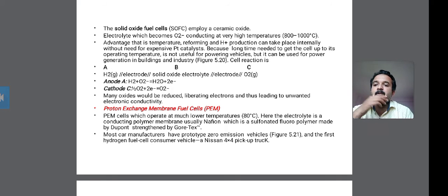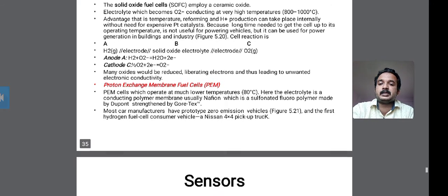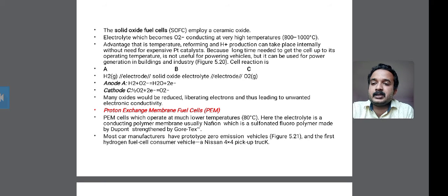Lastly, the proton exchange membrane fuel cell, known as PEM. The PEM cell operates at a much lower temperature, about 80 degrees Celsius. The electrolyte is a conducting polymer membrane, a sulfonated fluoropolymer, usually Nafion by DuPont, similar to Gore-Tex.